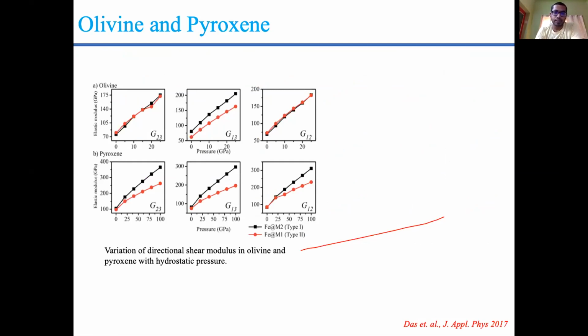First I want to say, as C55 is directly related to the directional shear modulus along the C axis on the BC plane, we directly get the consequence in the directional modulus G13. It is the same effect as C55. In pyroxene, it is also the same, we can see the same effect as C44, C55 and C66.